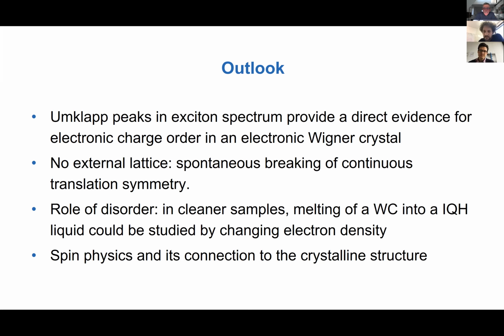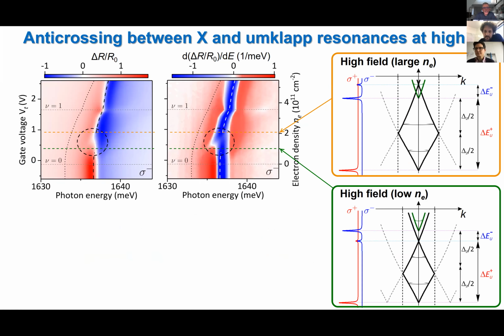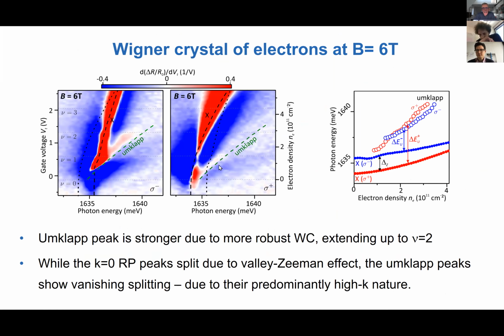Yeah, so the lattice constant is directly determined by the density, right? So because we have a certain density of electrons that basically sort of form a crystalline structure to minimize their Coulomb repulsion. And as we change the density, the lattice constant is changing. And in our case, this is ranging, if I remember correctly, between 30 and 10 nanometers. And according to your explanation, it has nothing to do with any potential Moiré superlattice imprinted by HBN encapsulation? We're almost absolutely sure about this because basically the HBN and TMD lattice constants are so different that any Moiré potential would have a periodicity on the order of 1 or 2 nanometers. So I think we can really exclude that.